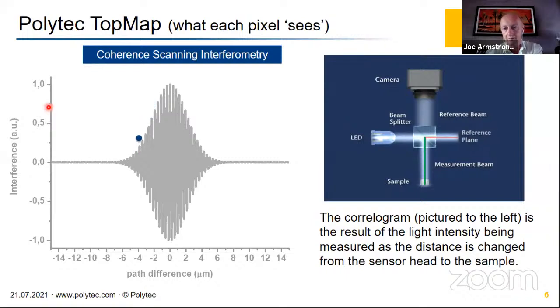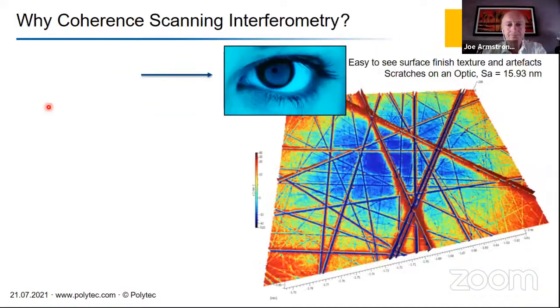So we have the test and the reference. And then we change the distance of a reference plane. By changing the distance of a reference plane, we can start to look for the best focus of a surface. And as we collect information coming back from the surface, we can then signal process this. And we can collect information and we have sensitivity to the sub-nanometer region. And we can get that over quite long measurement ranges as well.